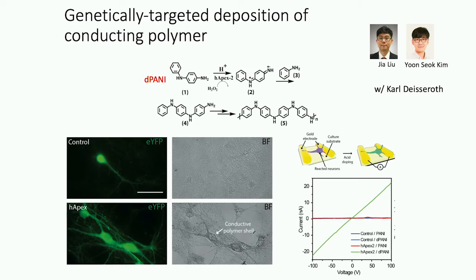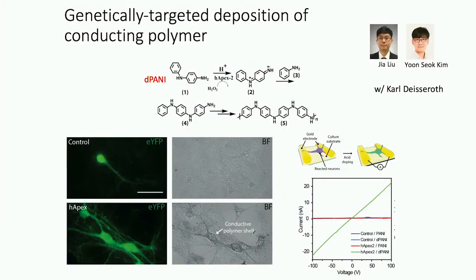And then these targeted cells will carry an enzyme that can initiate the polymerization of our conducting polymer. So only the region that's genetically targeted will be coated with the conducting polymer of interest. So on the top, those neuron cells are not covered with this enzyme, but on the lower part, the surfaces are covered with the enzyme. And then you see some darker regions. These are the conducting polymers that have initiated growth, and then they grow onto the neuron of interest. And indeed, these are conducting polymers. We can actually measure conductivity.